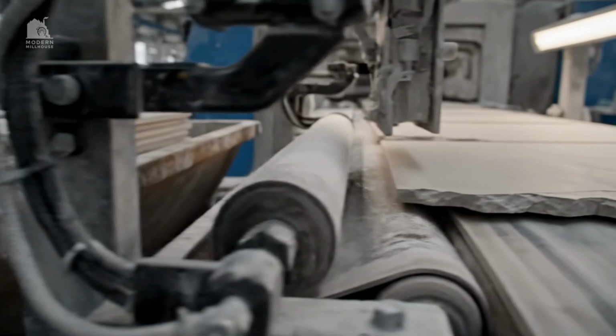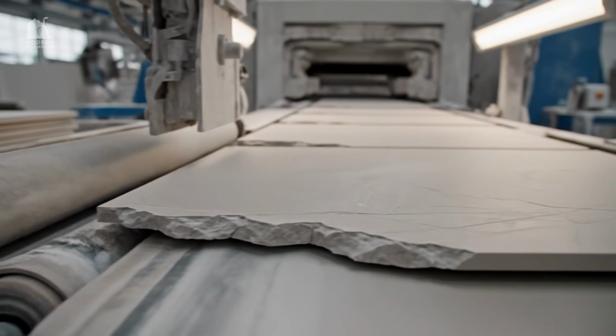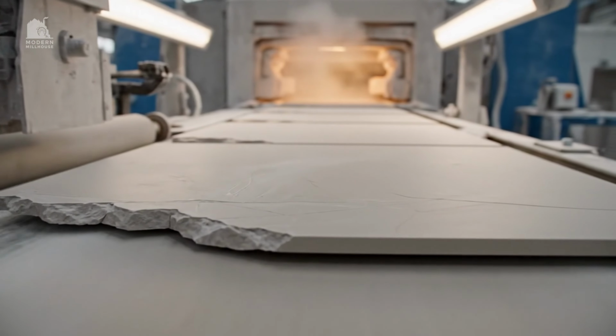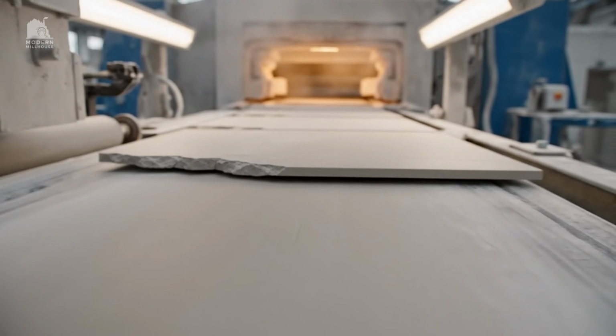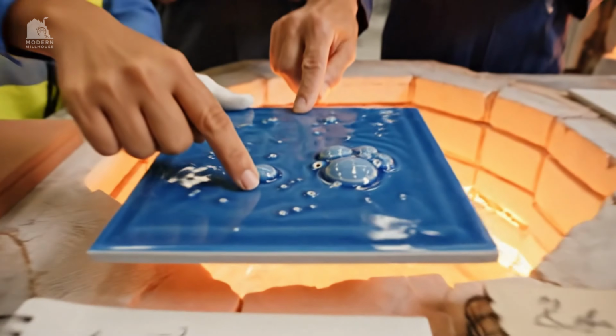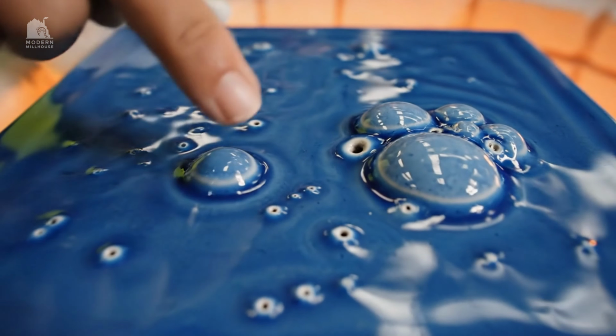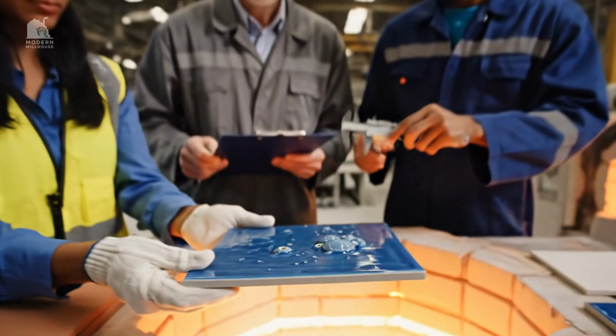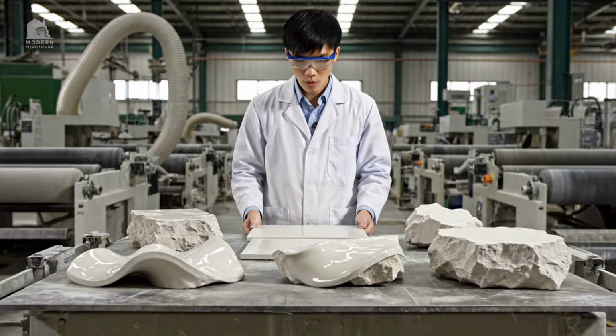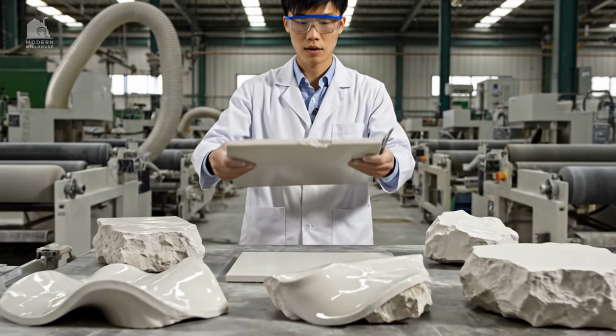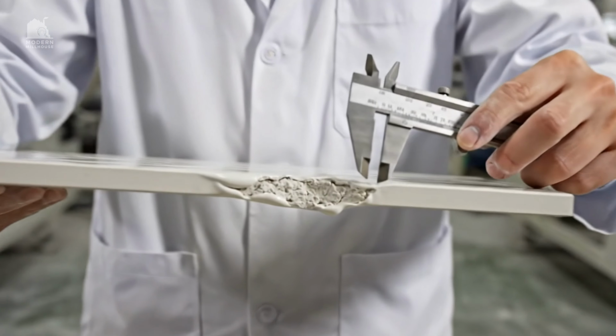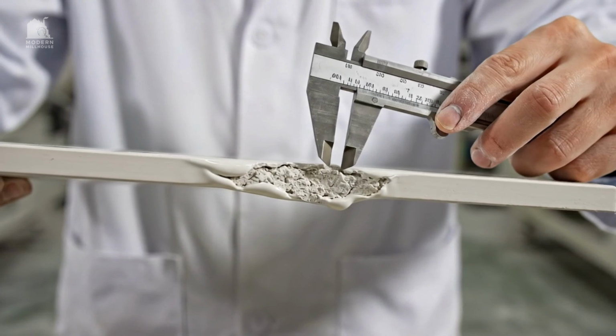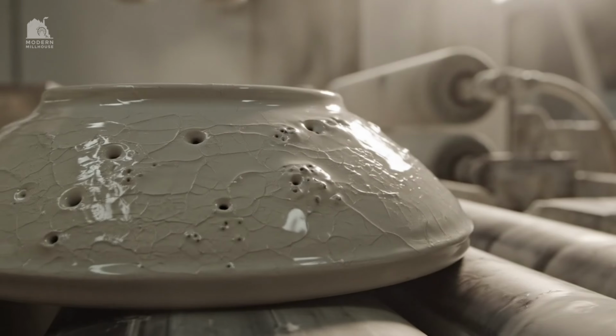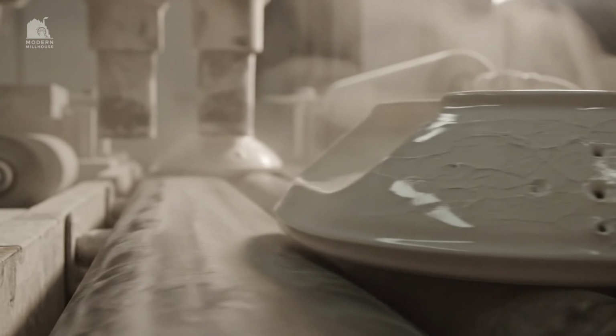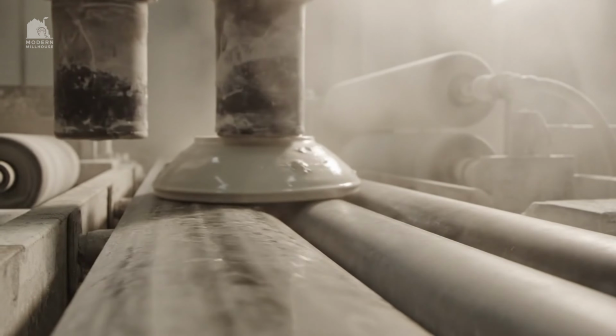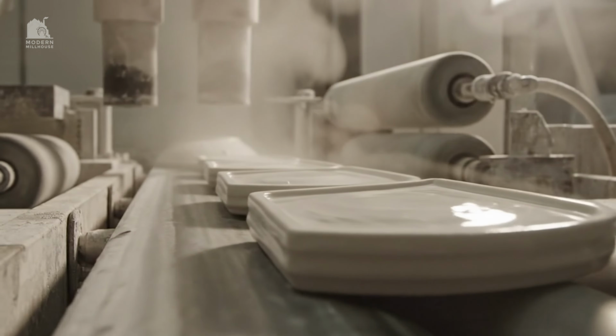Warping can come from uneven pressing density, uneven drying, or uneven heating across the kiln width. Pinholes appear when gases rise through the glaze during firing, leaving tiny craters. Blisters form when gas pressure lifts the molten glaze into bubbles. Crawling happens when glaze pulls away, often caused by dust, oil, or an incompatible surface that the glaze cannot wet. Crazing is a web of micro cracks that can develop if glaze and body shrink at different rates during cooling.